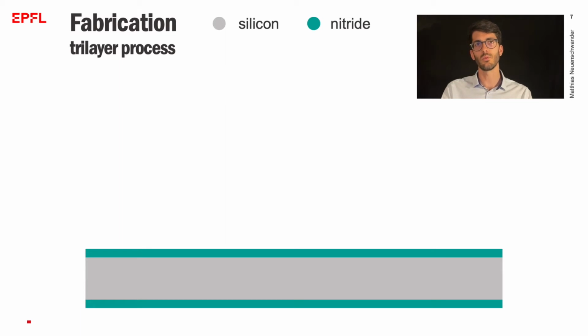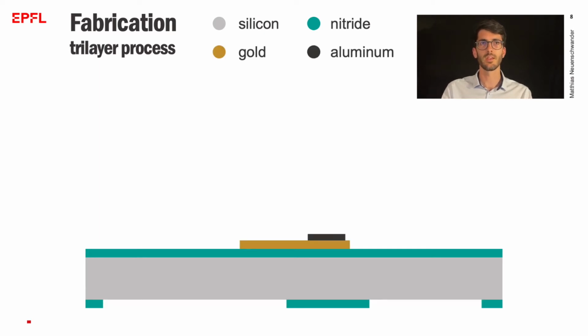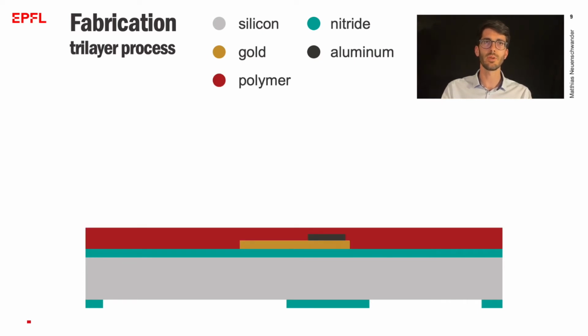I will now walk you through how such cantilevers are fabricated. We call this the tri-layer process. We start with a silicon wafer with a silicon nitride thin film, typically less than 100 nanometers thick. Next, we use 2 lift-off steps to pattern the gold heater and add an aluminum cover on the wire bonding pad. We then spin coat the polymer, a BCB solution commercially available under the name of cyclotene. This polymer can be used for wafer bonding and can also be dry etched. The coated layer is typically a few micrometers thick.